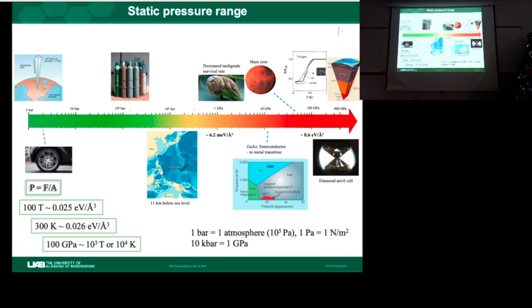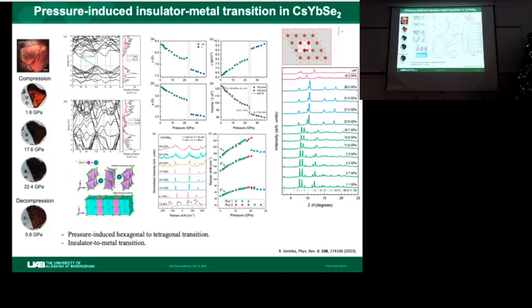Just for comparison, roughly 100 Tesla is about 25 milli electron volt per angstrom cube, and 300 Kelvin is about 26 milli eV, and 100 GPa is equivalent to about 1,000 Tesla or 10 to the 4th Kelvin. That gives you some sense.